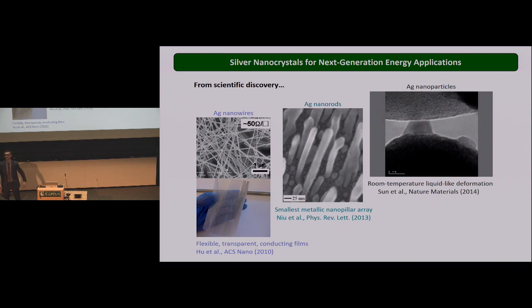Well, when you're comparing platinum and silver, they're not the equivalent fraction to the melting point. Do you have the comparison that equal fraction to the melting point? So yeah, their melting point is different. Silver is about 1250 Kelvin and platinum is 1800 Kelvin. So there are two ways we can do this.